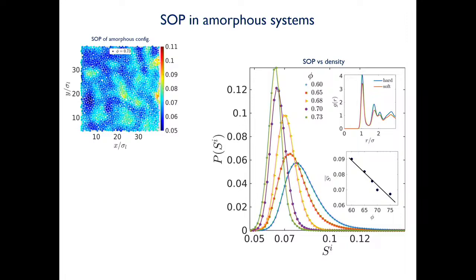Now that we have particle-level information, we wanted to check an idea: if you have rearrangements in the system, if you have an amorphous configuration, there could be certain regions that are soft and certain regions that are hard based on the local configuration, the local neighborhood. Just to check that, we picked all the soft particles in the system and grouped them, and then all the hard particles, and then we looked at the local g(r) for the hard particles and then the soft ones.